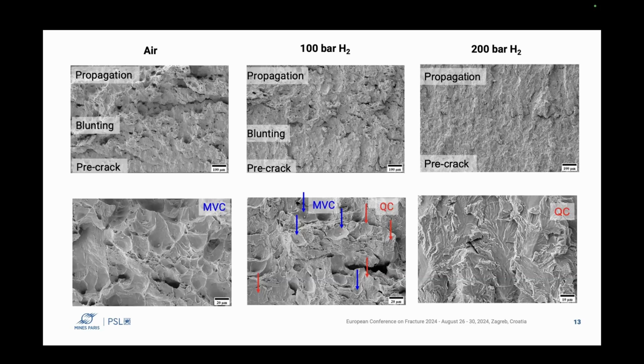When we look at 200 bar, there is no blunting zone here. We can see that the crack goes directly from the pre-crack to the propagation, and the beginning of propagation is 100% quasi cleavage. That is coherent with the popping we see in the plots.